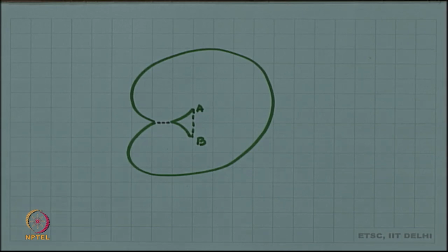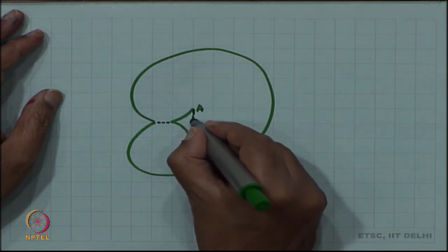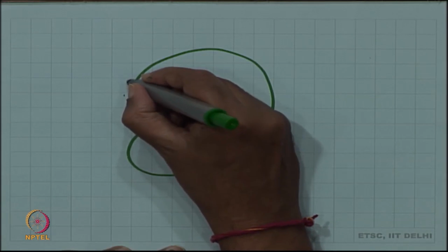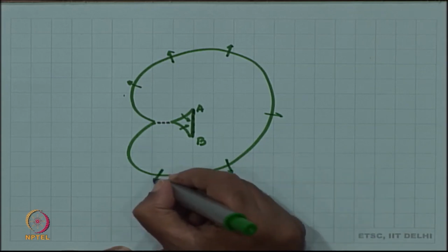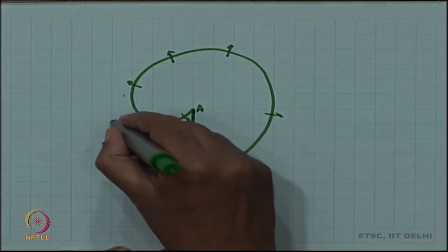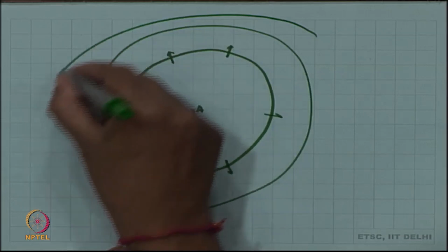So, you can see now that when this segment will relax, it will come back to its original position, because it will keep feeling force like this, and finally, it will come back to its original position and will be ready to generate another loop. Whereas, this loop which is created is still feeling normal force all along its length and will keep expanding into larger and larger loops.